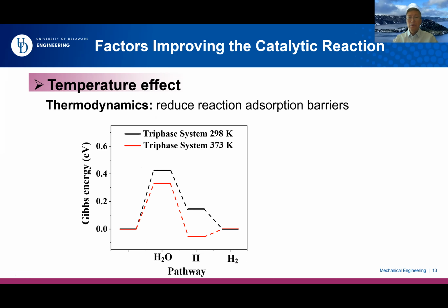The temperature effect works through two different perspectives. One, the thermodynamics, which of course can reduce the reaction adsorption barriers. For example, through calculation, we simply compare, in this case, liquid water. You can see that by simply increasing the temperature, you reduce the adsorption barriers for hydrogen. For the water molecule in this case, and also the hydrogen molecules also reduce their energy.